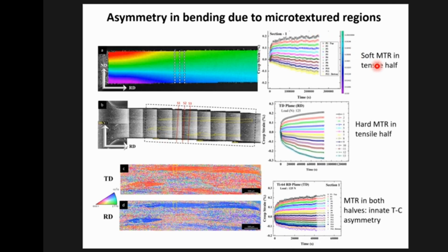So if you have a soft MTR in the tensile half, the tensile strains are much larger than the compressive strains. If it's reversed, the compressive side becomes stronger or more deforms more than the tensile side. If the MTR is on both sides, but you're pulling along the C-axis, then the beams are differentiated not because one half has an MTR or not, but because tension and compression are different when you pull along the C-axis. So it's a hideously complicated exercise, and that's what you see in the last, where the tension side has a strain of about 0.2 and the compressive side 0.15.